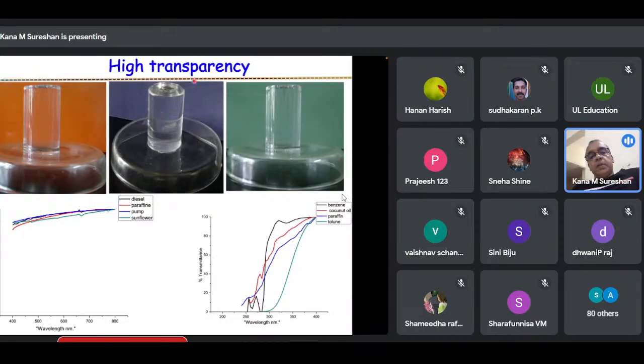Of course, you can use this material to make different kinds of jelly matter. This is a cylinder, a jelly cylinder made out of oil. And this is the UV-visible spectrum. You can see this is the visible region, 400 to 800 nanometers, and in that, the transmittance is very high, almost 90% in this visible region of the spectrum.